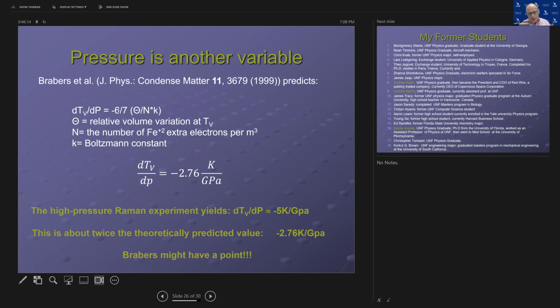So the high pressure Raman experiment yields a slope of the line that is around 5 Kelvin per gigapascal. What Brabers predicts is about half of that. Now you can ask, well, that's not such a great agreement. Well, in condensed matter physics, agreement within an order of magnitude is considered to be good. So even though this agreement is not ideal, it's pretty remarkable. So that is an argument in favor of the charge ordering-based mechanism of this transition.